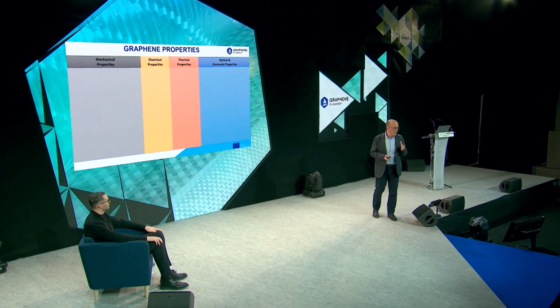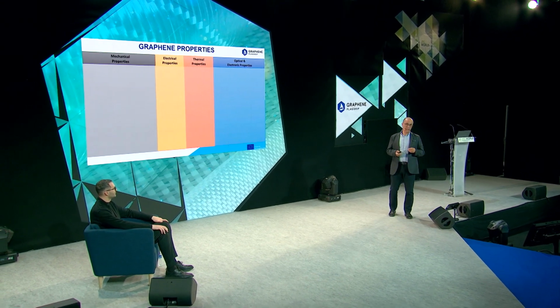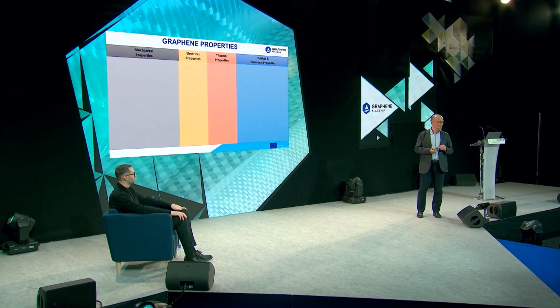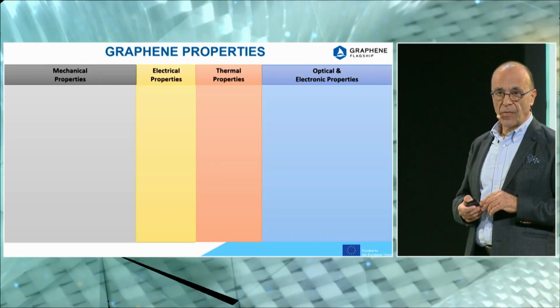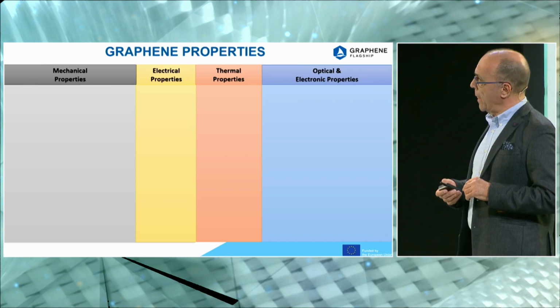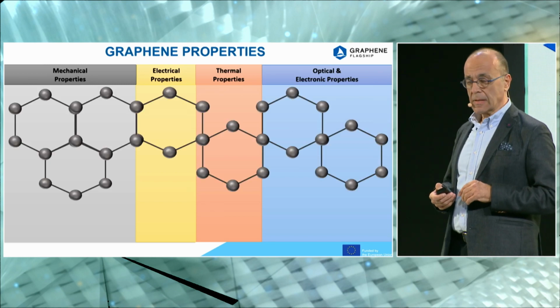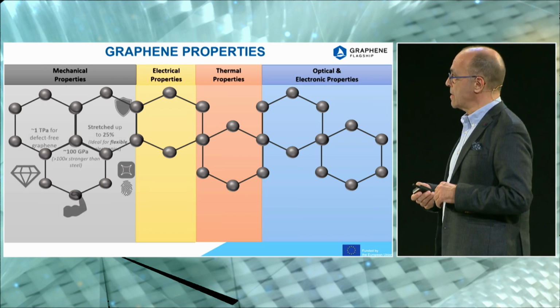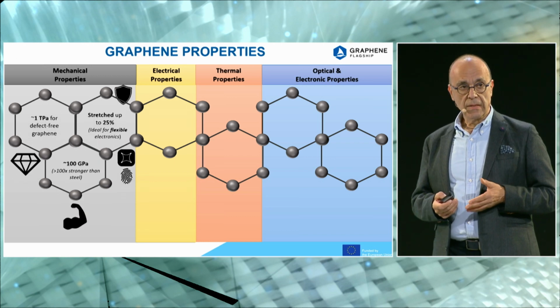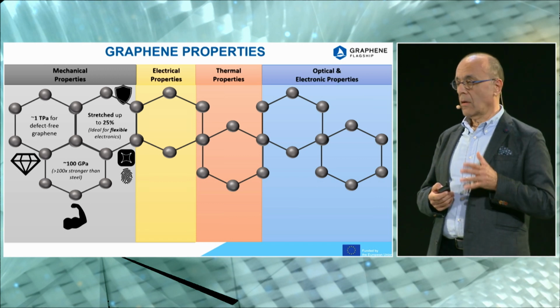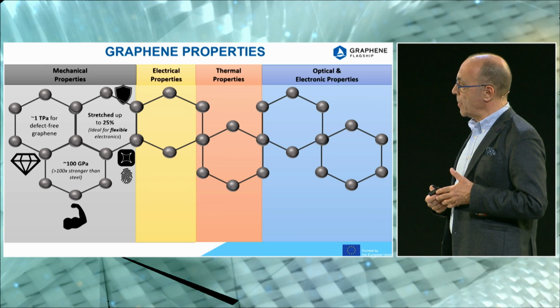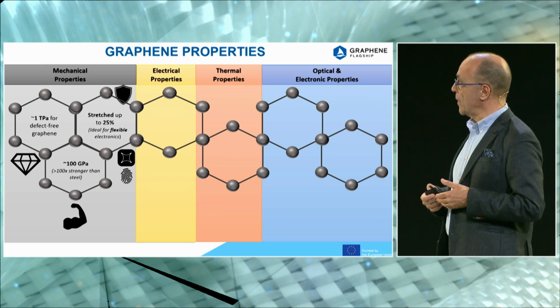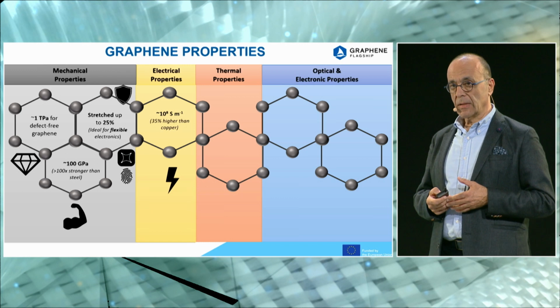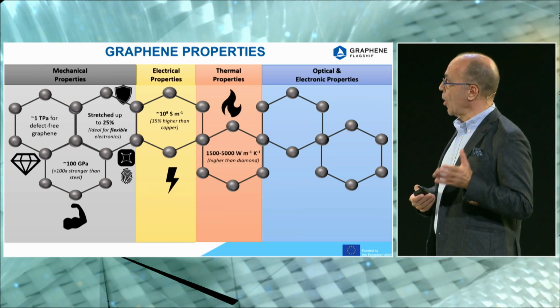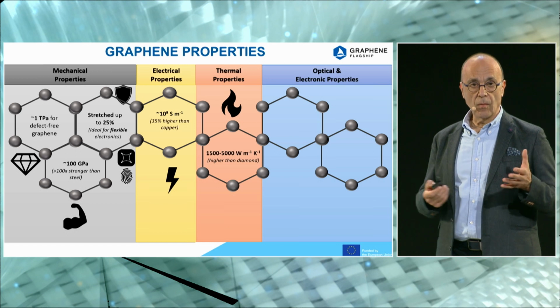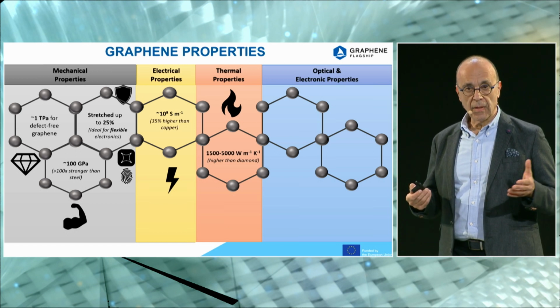Some of you may not be aware of what graphene is. Graphene is a monoatomic material which has a very small thickness, just the size of an atom. And it has these amazing properties: very high mechanical properties, 1 terapascal, the highest stiffness, strength of around 100 GPa. It can also be stretched up to 20-25%. Very high electrical properties, better than copper, thermal properties, excellent properties. So it's like the holy grail of the material.